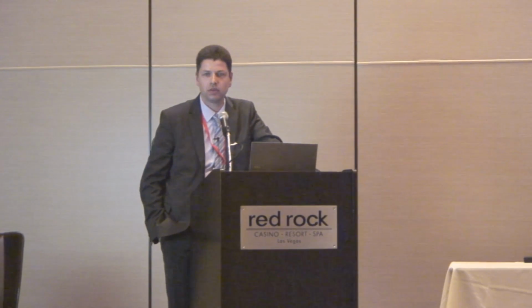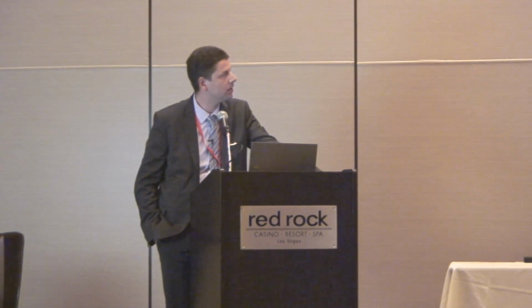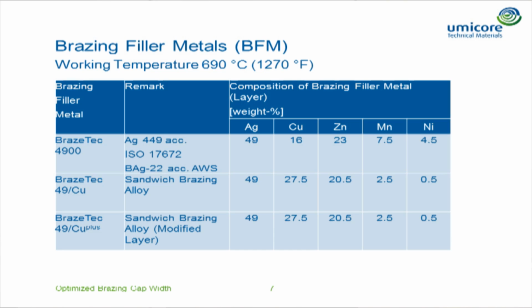We used these three different kinds of brazing alloys. One was the normal brazing alloy, Ag 449 according to the ISO standard, or BAg-22 according to the AWS. And later on it will always be called BFM449 when you want to follow. And two different kinds of sandwich brazing alloys. One is a normal sandwich brazing alloy with pure copper inside, and the other one is with a modified layer in between.